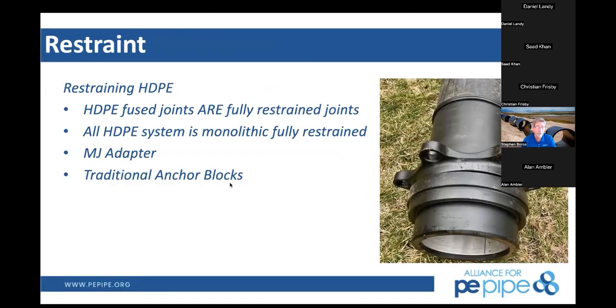We talked earlier about restraint. So first of all, a fused polyethylene joint is considered a fully restrained joint. Once that is fused together, it's a monolithic system now. The 2 pieces of pipe that you butt fuse together now becomes 100 feet of pipe. There's essentially no joint left in that pipe. We all know this. It's a great benefit of polyethylene, putting long strings together that are never going to leak at those joints. They're not going to be the weak link in your system.